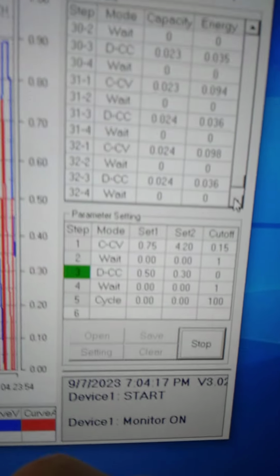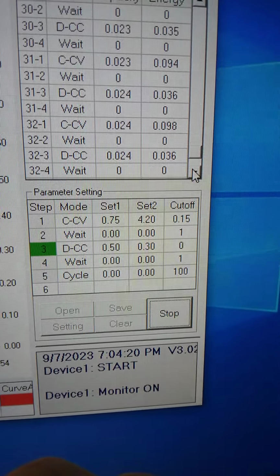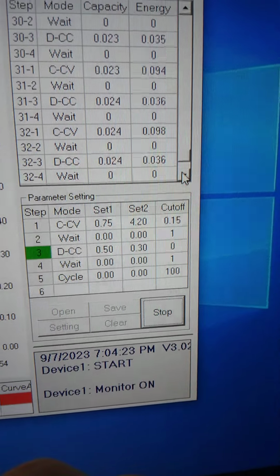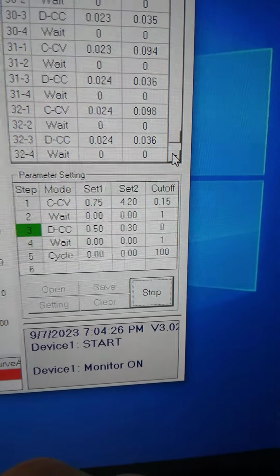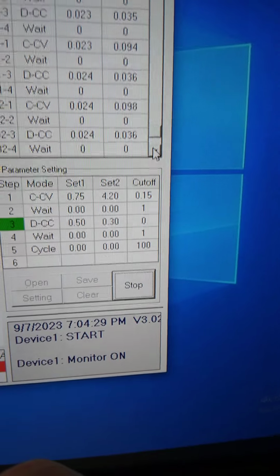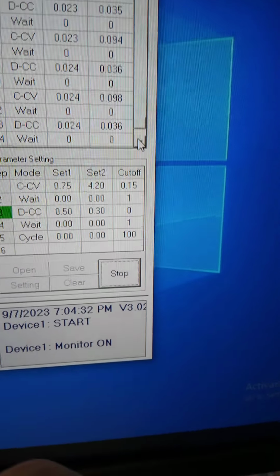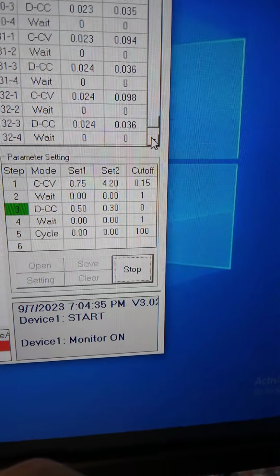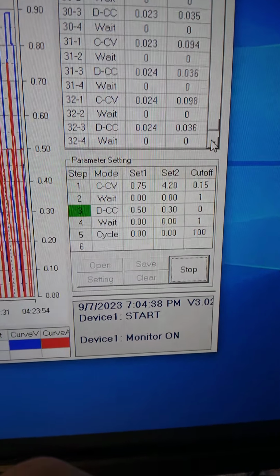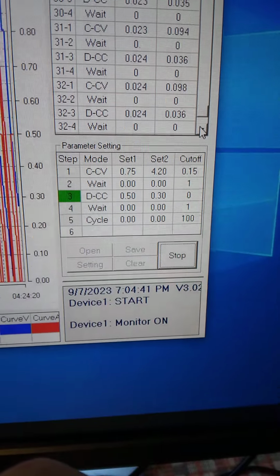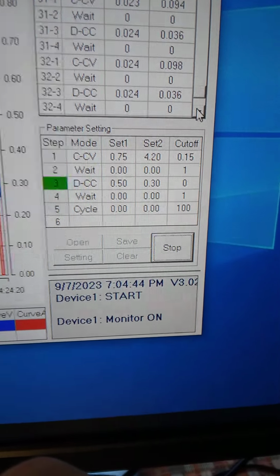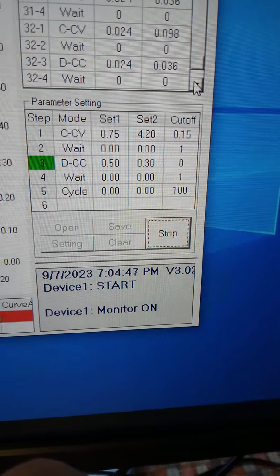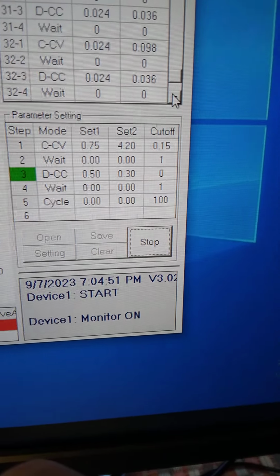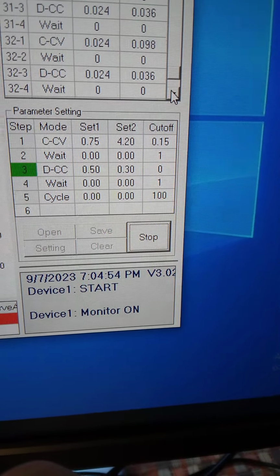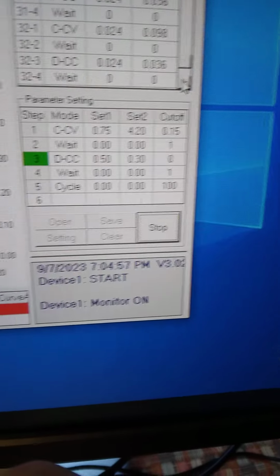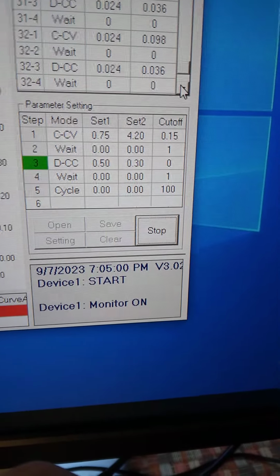And you can see, here's my input of values. I'm charging up at constant voltage, 750 milliamps. And I bring it up to 4.2 volts in series with the two supercaps. And then I use a trickle charge and I cut it off at 0.15 amps. I give it a wait period of 1 minute, and then a discharge at constant current. And I bring it down at 500 milliamps. And then I cut off at 0.30 volts. Then wait a minute, and I'm doing 100 cycles.